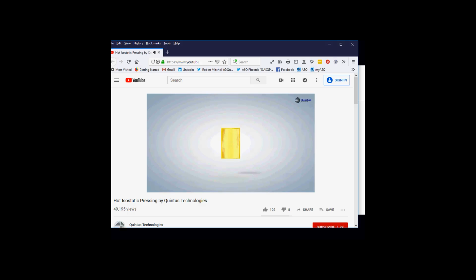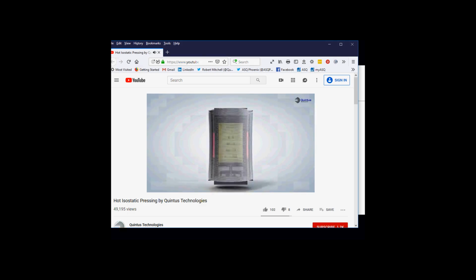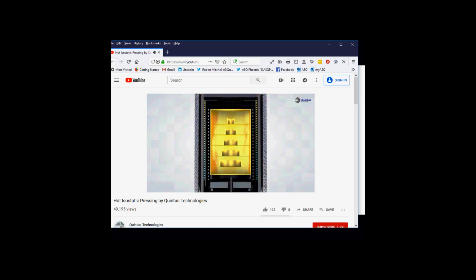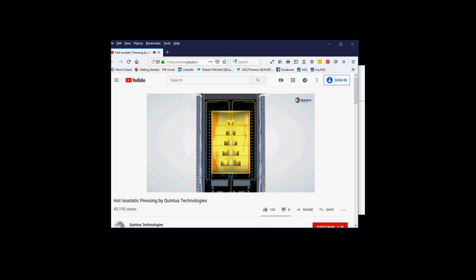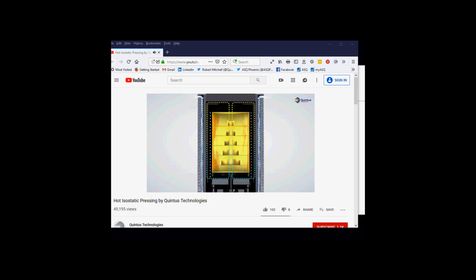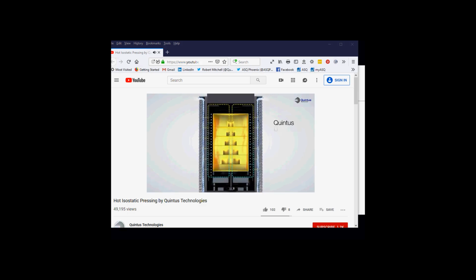But combining quick cooling with high pressure places stringent demands on the pressurized furnace. The vessel needs to be robust enough to withstand the high pressure, while also being cooled quickly from the outside. By adding a wire package to the outside of the vessel, both can be achieved. The wire package allows the inner wall to be thinner for quicker cooling, which maintains the structural integrity of the pressure vessel. The thinner wall enables a unique heat exchange system, which makes it possible to cool down the load quickly and meet the requirements of the heat treatment process. This means that the HIP process and the heat treatment can be run at the same time in the same vessel, saving time and energy.